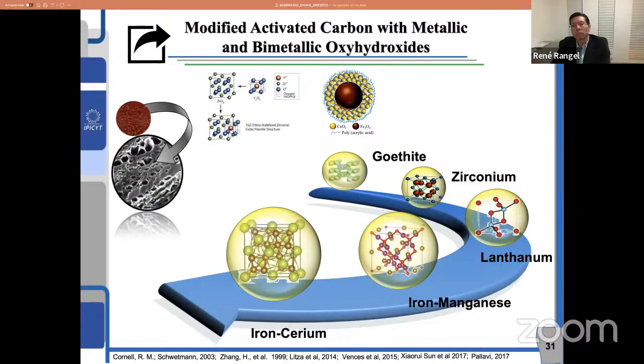Also, apart from using metal oxides like iron and lanthanum, in the last year we have anchored mixes of metal oxides like combinations of iron and manganese, iron and cerium, zirconium and cerium, and we have obtained a very good material. We just published the results, a material with a very high capacity of more than 180 milligrams per gram, which is quite a lot, and we just applied for the patent, and so we are very happy for that. Another advantage of using mixes of metal oxides is that these will be more stable. In other words, they will not leach as easily. And we will also have very amorphous materials with higher surface area. And this will give us much higher removal of arsenic.